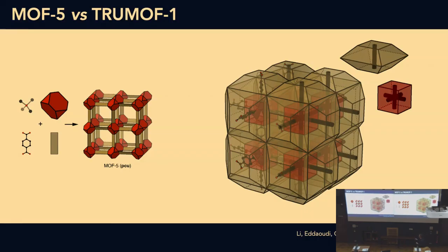And here what we're doing is we're decorating those blocks from the underlying chemical connectivity. Okay? So here, this little octahedron in the middle is because we're going to have octahedral connections. And notice that this connectivity, here's the linker that bridges 2, doesn't break the symmetry. So when I take copies of those blocks and put them together, there's a single way of doing it. And the connectivity that you produce of these connected little octahedra is the same connectivity as the underlying metal-organic framework. Okay, so there's no disorder. The propensity for order is encoded in the blocks.